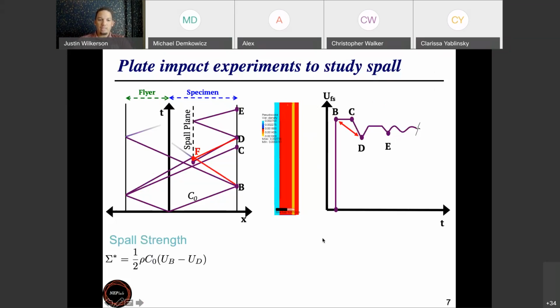So one of the key metrics that we're most interested in is the so-called spall strength. And the spall strength is an indication of the maximum hydrostatic tensile stress or the maximum longitudinal tensile stress that the material sustained before it failed. Okay, and the way that we calculate that from this free surface velocity history is 1/2 the mass density of the material times the bulk wave speed times the difference in these two velocities that are measured on the back face: the velocity at time b, which is this velocity here, minus the velocity at time d, which is this velocity at the bottom of the trough before you start increasing again.